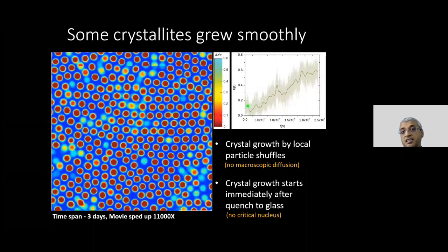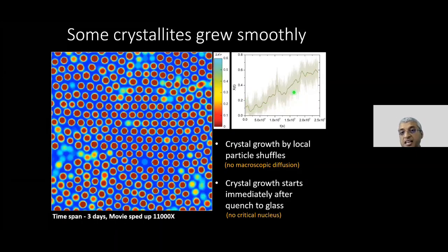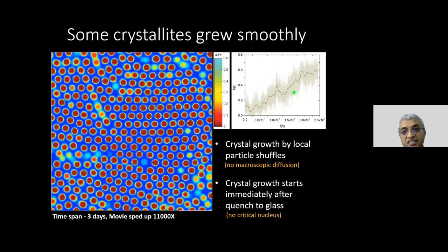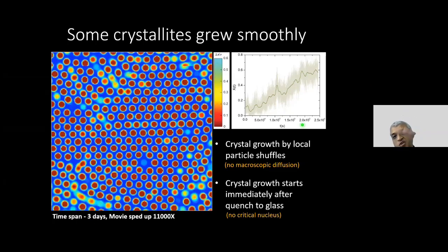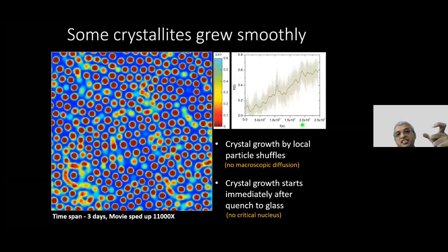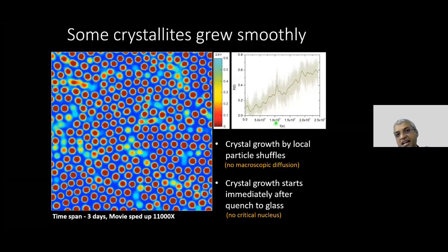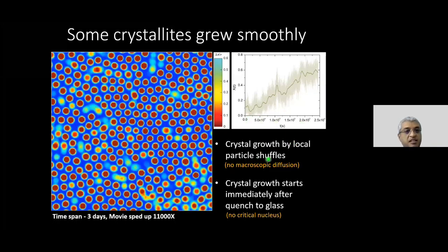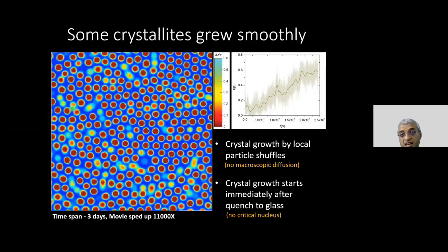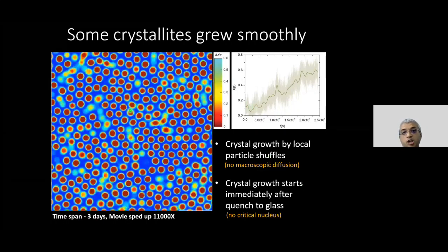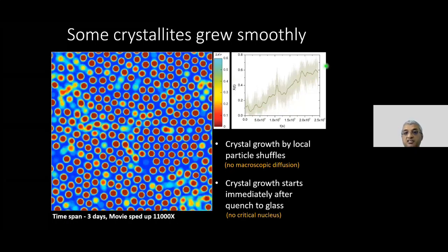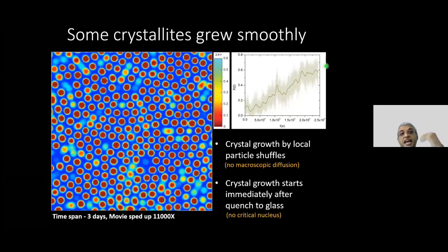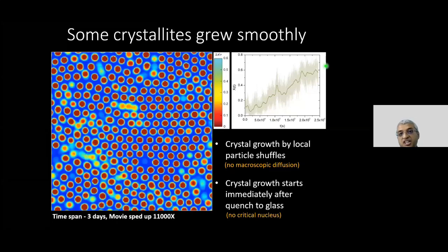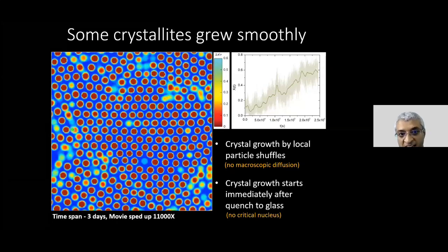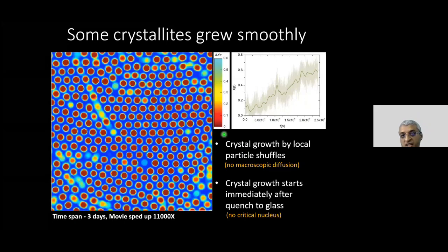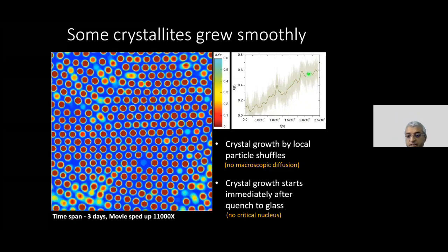And the key thing to note about this profile is that if I had crystallization happening from a liquid, because I have to cross an activation barrier, there would be a certain time for me to do that. It's sometimes called a nucleation time. Except in a glass, what I see is that the minute I do the quench, I start seeing this increase in crystallinity. Okay, so the x of t that I had shown you earlier was an average over all crystallites, but if we were to dissect what each individual crystallite is doing, one growth process is via this.